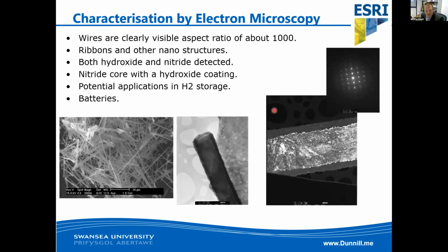Electron diffraction here shows that we've actually got lithium nitride in the middle, surrounded by a shell of lithium hydroxide. These actually have very interesting applications in hydrogen storage. So for instance, these things will take up about 11.5 weight% of hydrogen, which is pretty significant. And if you start intercalating different materials like carbon and molybdenum and cobalt into the ends of these fibers, you can actually form nano batteries with the lithium nitride. So there's lots and lots of potential there.